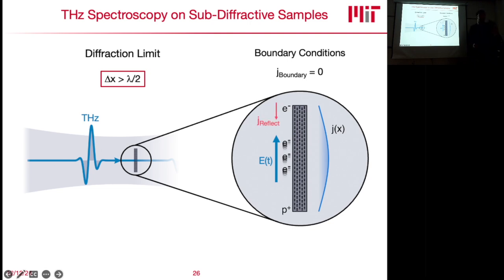What will also happen is that if you start accelerating your electrons into the boundary, they will start getting reflected back. So we basically start getting a current that moves the other way. And so what can actually happen is that this incoming current that is propelled by your electric field and the reflected current can lead to standing wave patterns in your material, which give rise to counter-propagating currents with respect to your electric field. So up here, you have a current that moves this way, and down here in the lower half of the sample, you can actually have a current that goes the complete other way compared to your electric field direction.